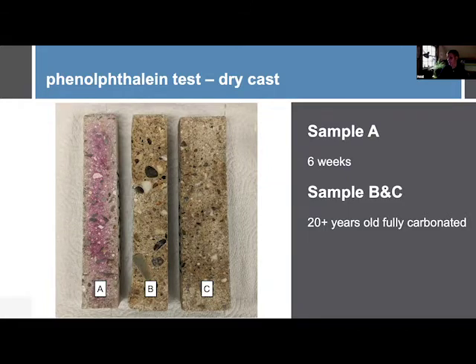So I had preliminary TGA testing done on these samples, and this testing tells us that sample A had a sequestration rate of about 13 to 17%, and that 13 to 17% is the percentage of the total amount of CO2 given off during cement production for the cement that was used to make this block. The 20-plus-year-old concrete, which is fully carbonated, showed TGA testing of about 25 to 28%. And just a little note here, and I am going to get into this a little more: roughly, the potential to carbonate is around 45%, and that's due to the amount of CO2 emitted during the chemical reaction breaking apart the limestone.